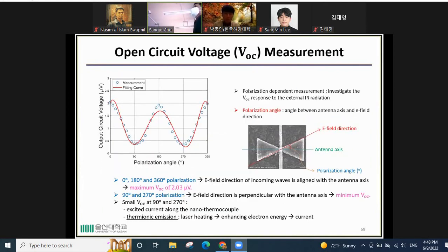And this is the open circuit voltage measurement of our device. This measurement aims to investigate the VOC response to the external infrared radiation. From this, this is the output circuit voltage as a function of the polarization angle. The polarization angle is defined as the angle between the antenna axis and the electric field direction. So from this plot, we can see the maximum VOC of 2.03 microvolts happens at 0 degree, 180 degree, and 360 degree because the incoming incident wave is aligned with the antenna axis.